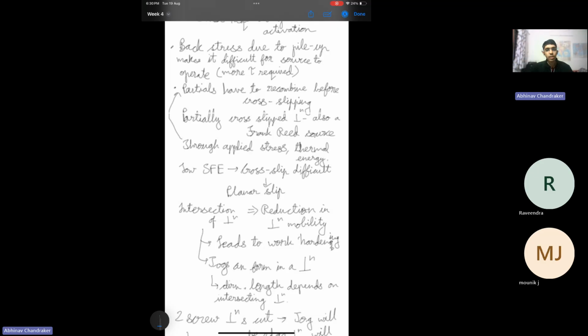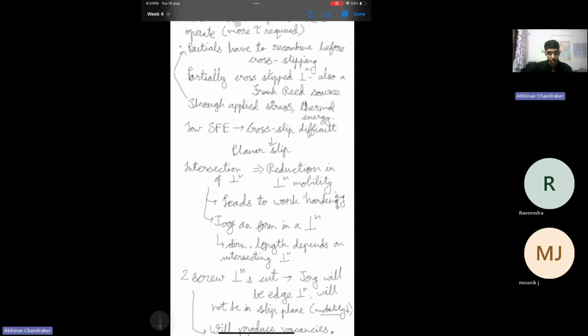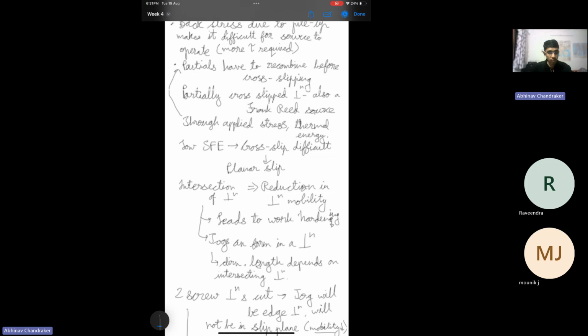But one other aspect related to the Frank Read source is that over time, as the dislocation loops form and pile up, they will repel the incoming dislocations which are coming towards the obstacle or the source. So the more dislocation loops form, the more they will repel the incoming dislocations, and as a result, they will make it difficult for the source to continue operating, since they have this repulsive force, which can also be called a backstress. The source will find it more and more difficult to operate. More stress will be required for the incoming dislocations to reach the obstacle.